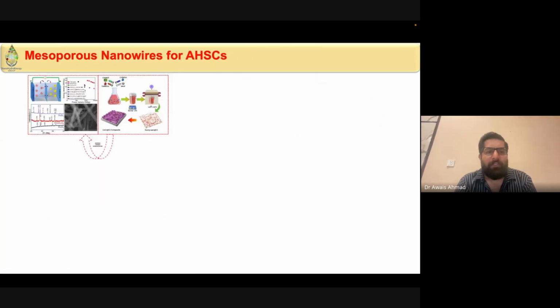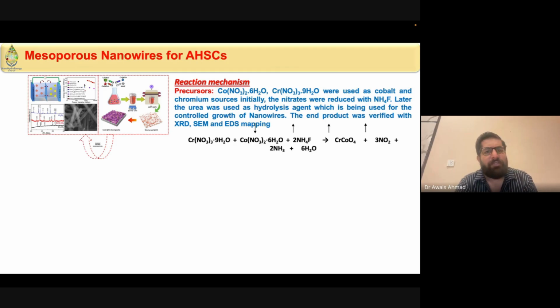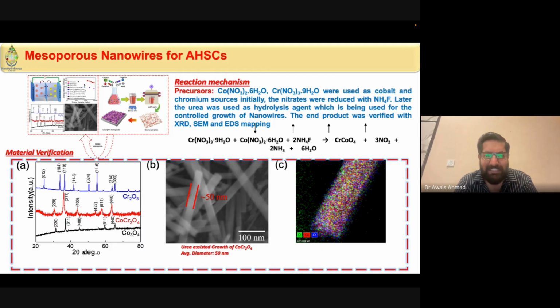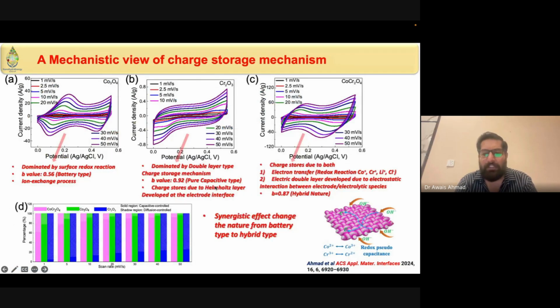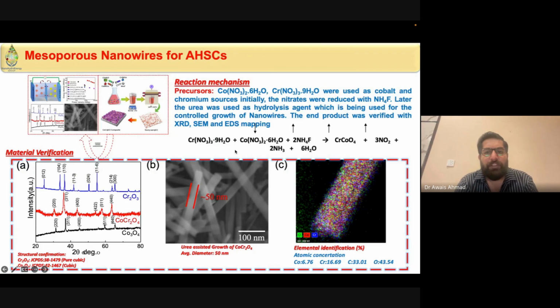This is one of the very favorite research papers which we published, and it's also patented in the US, that mesoporous nanowires we derived for the very first time. The first one we derived was with chromium cobalt. And with the chromium cobalt, we got very sharp nanowires of 50 nanometer. And if you check the elemental identification, you can see that we get cobalt 6% and chromium is near 16%.